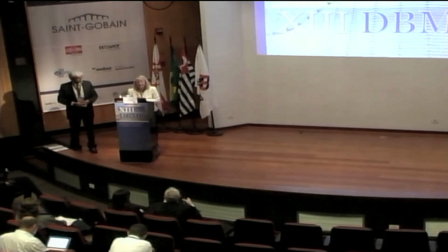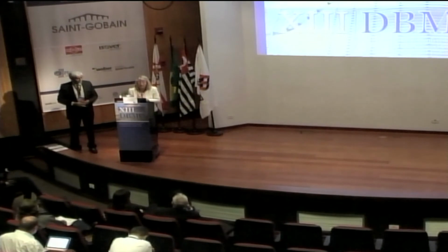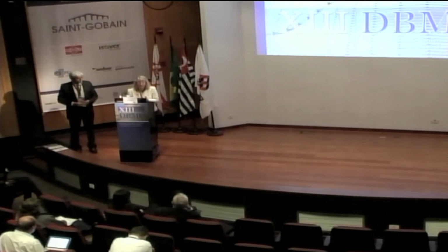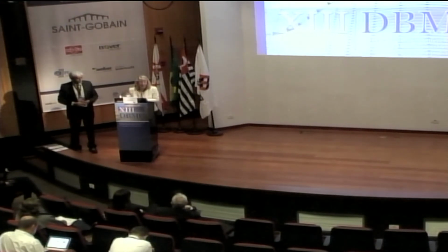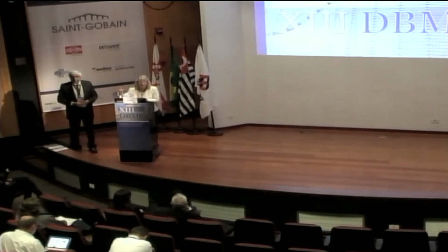Yeah, well, sorry, I had to concentrate, and thanks again for the questions. Carbonation is much less affected by the aging factor. That is clear. You may have a first period for the skin of the concrete, but after that it will depend on the humidity, whether you have the square root of time or not. If you have higher humidity, you will have less velocity of carbonation. In the case of Maracanã, it's very particular. It was very interesting for me.